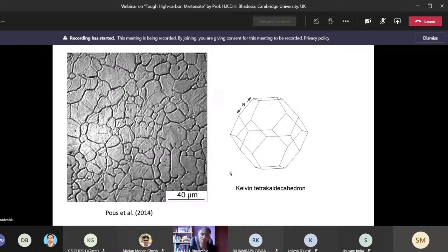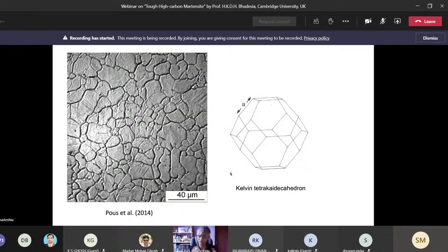Now, we cannot actually produce an austenite grain size which is 1/4 of a micrometer just by doing this heat treatment, where we austenitize and have a microalloying addition to control the austenite grain coarsening. It's impossible to produce a grain size which is 1/4 of a micrometer just by heat treatment. But there is this wonderful process where you have a rolling mill and you end up with a final grain structure which is pancaked if you use a low rolling temperature. Okay, the hot rolling of the austenite must be conducted at a relatively low temperature, something of the order of 800 degrees centigrade.